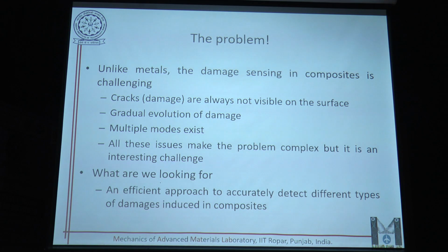So what is the challenge here? Unlike metals, there are a lot of good techniques available like radiography or CT scan, where we can detect damage during quality control at industry scale. But composites are a completely different ball game altogether. Why? Because they are inhomogeneous, they are anisotropic, and that creates a lot of problems.